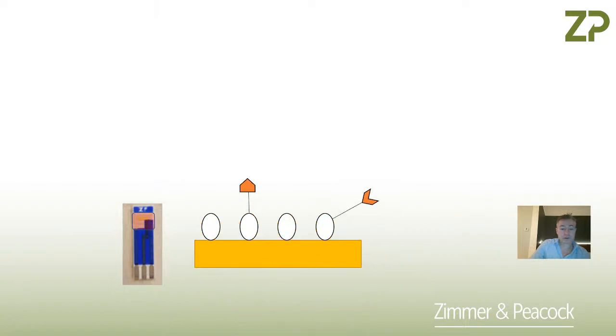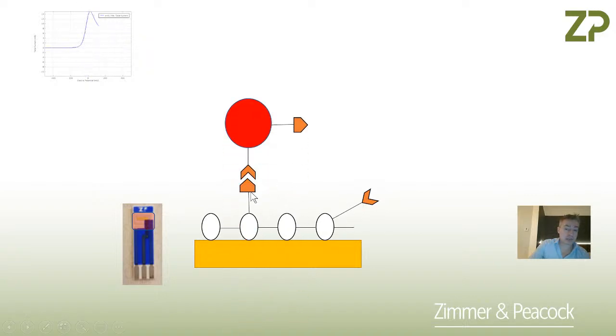Now, I want to contrast this with a final statement around these ideas, that you now take a mixture of monomers. Here we've got a neutral monomer, a monomer with a key moiety in it, and a monomer with a lock moiety on it. You can do cyclic voltammetry, which will start the polymerization process. And now you do that in the presence of the template molecule. This template molecule is more interesting, and this is typically like a drug molecule, that you might have an NH2 group, an amine group, and you might have an alcohol group. So you've got different functional groups.